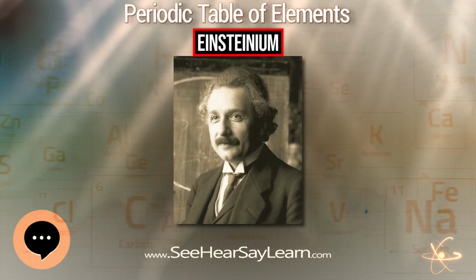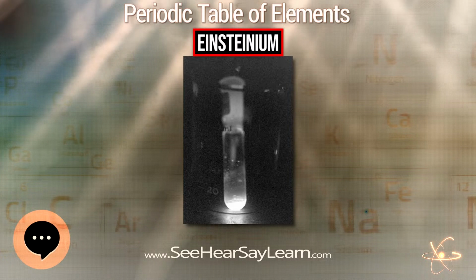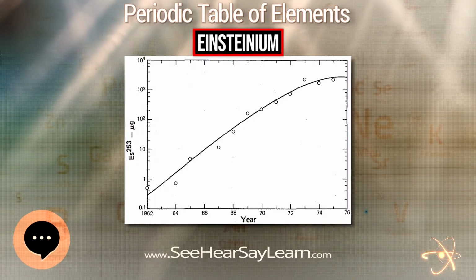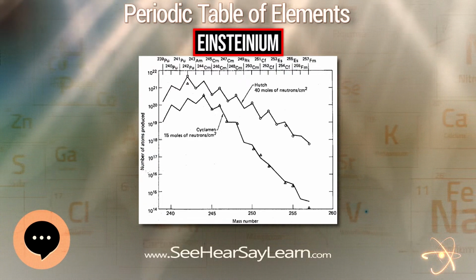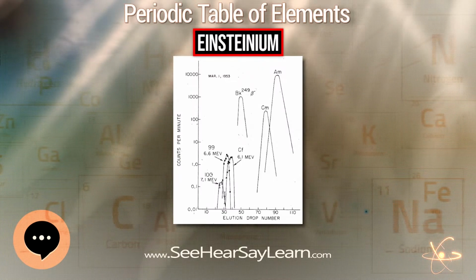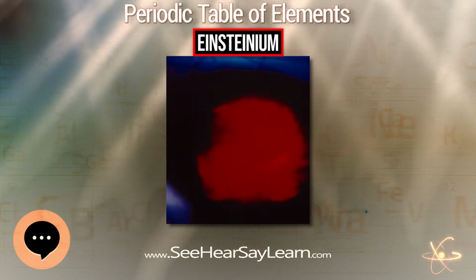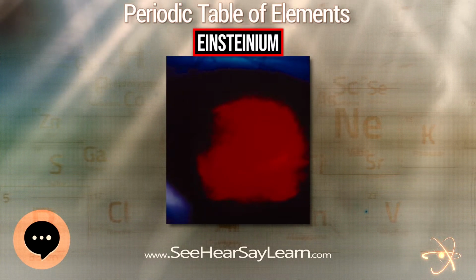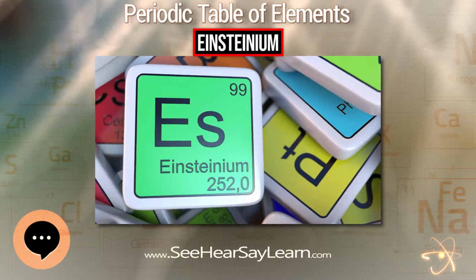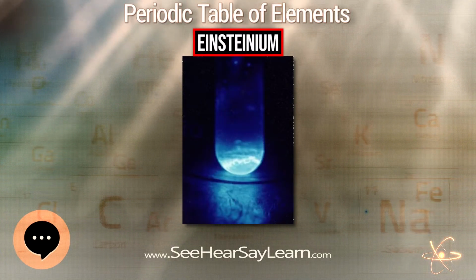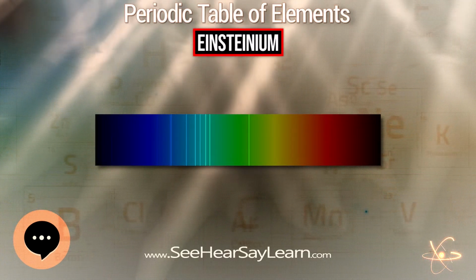Einsteinium bromide is a pale yellow solid with a monoclinic structure of AlCl3 type, where the Einsteinium atoms are octahedrally coordinated by bromine. The divalent compounds of Einsteinium are obtained by reducing the trivalent halides with hydrogen. Einsteinium chloride, Einsteinium bromide, and Einsteinium iodide have been produced and characterized by optical absorption, with no structural information available yet. Known oxyhalides of Einsteinium include EsOCl, EsOBr, and EsOI. They are synthesized by treating a trihalide with a vapor mixture of water and the corresponding hydrogen halide, for example, EsCl3 plus H2O/HCl to obtain EsOCl.